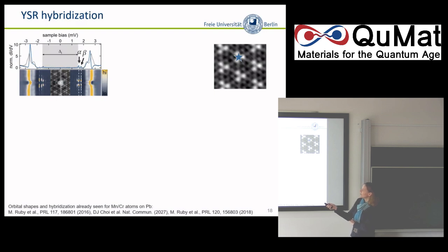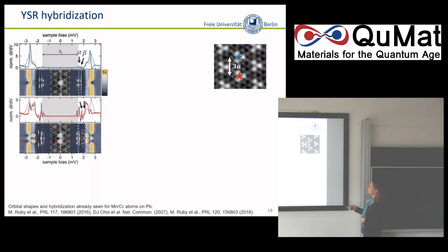And you see that there's the oscillation, and this is due to the fact that we have this oscillation with the Fermi wave. Okay, but notably alpha and beta are discrete states, and I will focus on these lower energy states more because there we see they are sharper in energy, so we can look more precisely at what happens if we put a second atom next to it. So next to this would mean like 3 atomic sites apart.